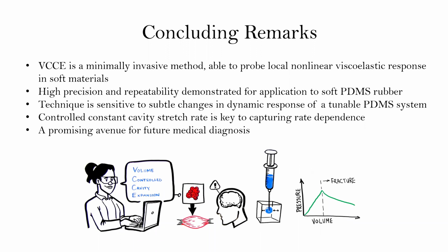So we realized that going to this initial relaxed spherical cavity and then doing the experiments was an important factor. And also realizing that we shouldn't go into the fractured zone, and how to come up with a single technique that probes all these different rates, and then one package routine that implements all these things, was probably the biggest challenge. The other thing was experimentally removing the errors, like the dynamic calibration that we need to do, and how we correct for surface tension so that we ultimately end up with repeatable curves when doing multiple cycles of loading. But maybe Tal can explain.